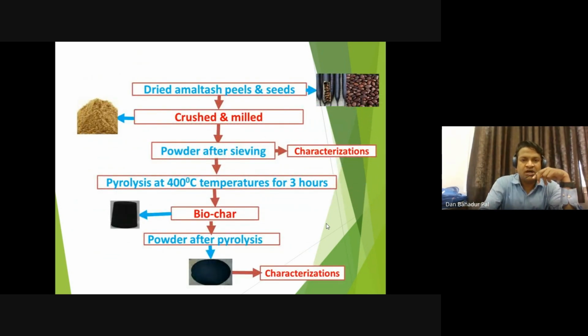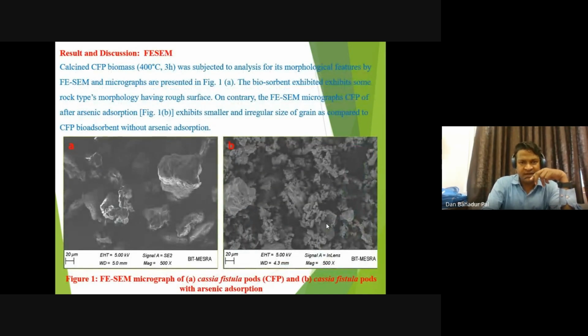This is the flow chart of the particular work for preparation of biochar. First, dry the amaltas peel and seeds, then crush and mill, then powder after sieving. Before calcination and after calcination we characterize it for elemental analysis, morphology, functional group, crystal size and crystal structure. Then calcine at 400 for 3 hours to make biochar for bioadsorbent application.